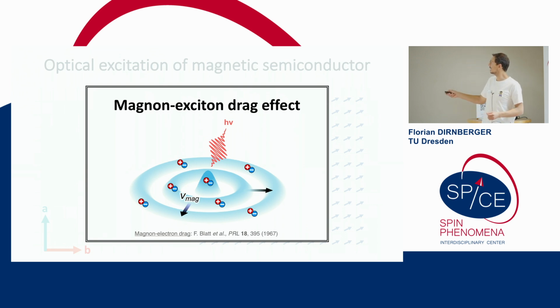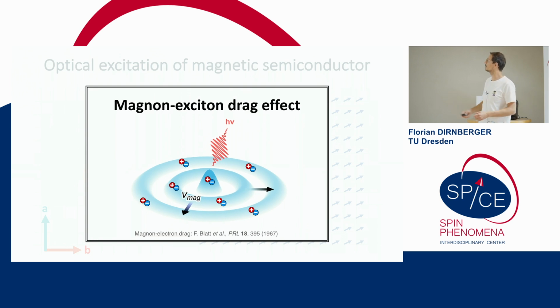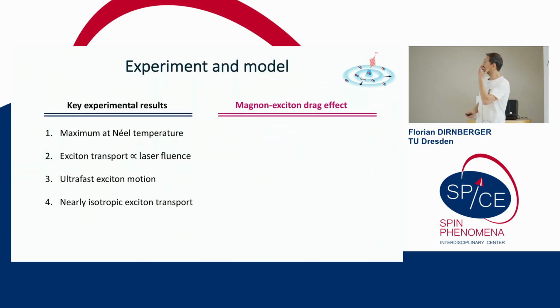The basic idea is that when you shoot a laser pulse, you locally create excitons, you locally create magnons. Now the magnons are going to move away from that excitation region very fast. And because the excitons and magnons are coupled in chromium sulfide bromide, the magnons can actually scatter the excitons. They can impart momentum. They push the excitons away from that excitation region. So this is the general picture that we have in mind when we think of these experiments now. And we feel like this allows us to explain the key signatures that we see.